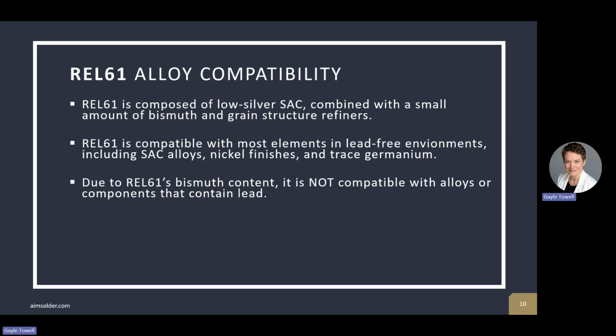However, due to REL61's bismuth content, it is not compatible with alloys and components that contain lead. And that's because bismuth can combine with lead to create sort of a really low melting eutectic that can cause joint failures. But as long as your process is lead-free, REL61 performs very well.